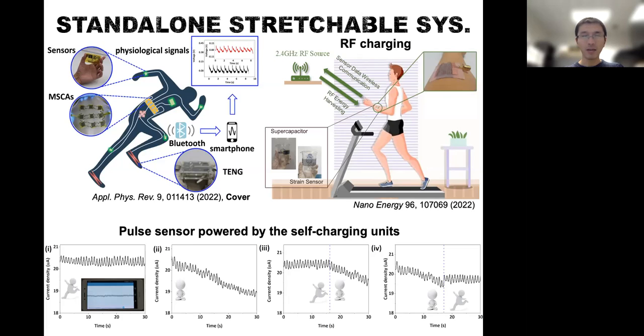So in essence, the highly porous structure, and here is not the laser induced graphene alone, but rather we can dope the material and also do the composite material design to infiltrate the material with additional decoration. For example, metal oxide and the other type of nanomaterials can be integrated onto the platform. But in general, the 3D scaffold provides a really high transport speed in terms of the ions and the electrons. So the charging can be really fast. And with the 3D pore structure, it can provide ample site for the charge storage. And so the energy and the power density can be higher when compared with some of the solid materials.